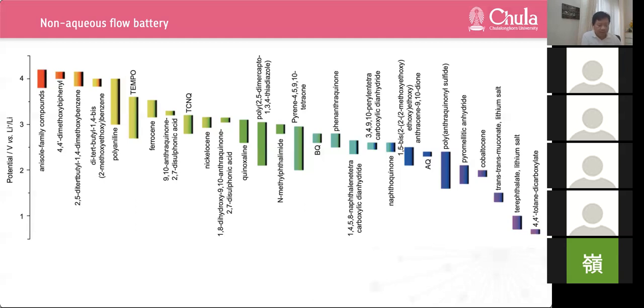However, most metal ligand and non-aqueous flow batteries suffer from low coulombic efficiency. That's a pain point for this class of system due to chemical degradation of the redox molecules and poor solubility. The most soluble transition metal complex examined for non-aqueous redox flow battery application involving multiple electron transfer reaches saturation at 0.8 molar in acetonitrile. Synchronous electron transfer complex reaches 1.8 molar in carbonate solvent. Acetonitrile and carbonate solvents are the mostly used non-aqueous electrolytes. Their energy densities are much lower than those of aqueous systems, although cell potential is larger.